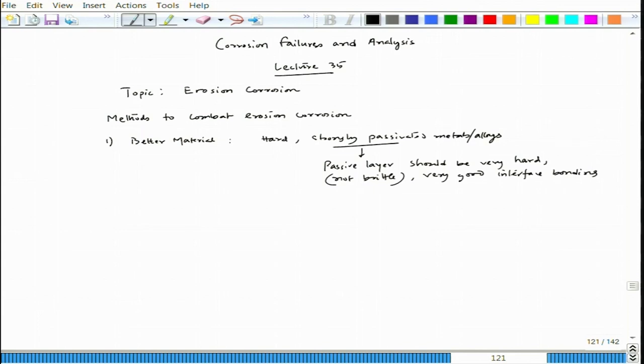So, like that way, what happens? Even if there is erosion factor, then definitely that passive layer would not get knocked off from any portion of that particular metal. So, that way we can protect it, and for better material we can think of 316SS, which contains molybdenum. Actually, molybdenum helps in preventing erosion corrosion. We can think of titanium. If you recall, with the velocity of sea water, even if the speed goes to around 27 feet per second, still the erosion corrosion rate of titanium as well as molybdenum-containing steel is very low. In case of titanium, there is hardly any erosion corrosion even at that speed of 27 feet per second of sea water. And in 316 also it is almost negligible. So, that way better material can definitely prevent erosion corrosion to a great extent.